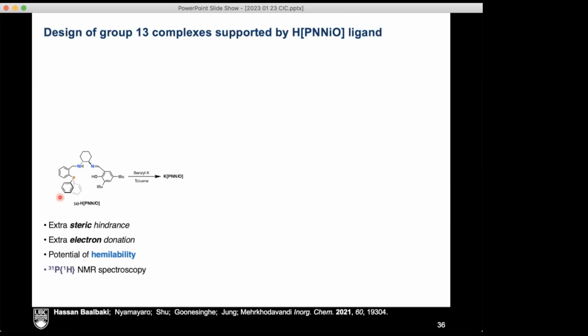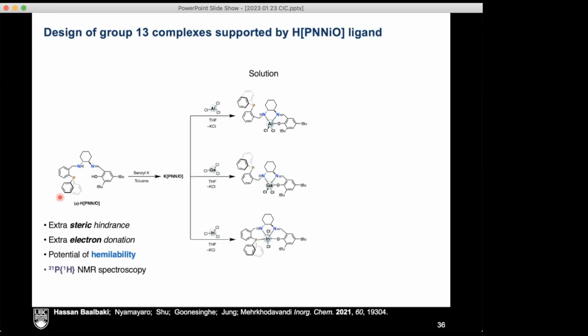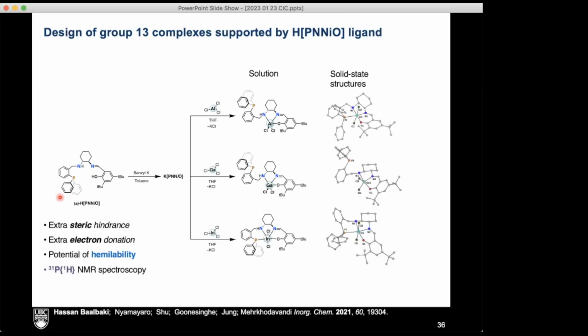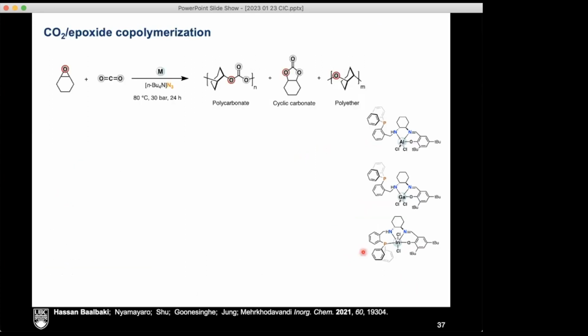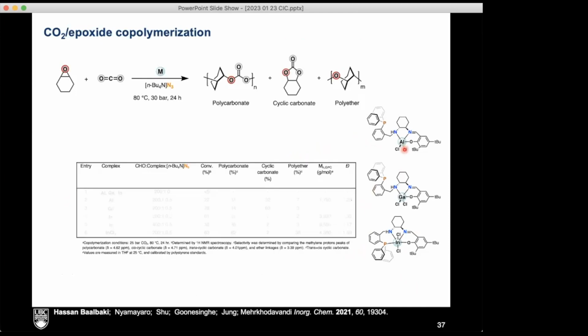And he rebelled and decided, okay, I'm not just going to work with indium, but I'm going to work with all of the group 13 to look at a comparison. Okay, fine. So he was able to isolate all of these compounds. And what he was able to show is, interestingly, that for the aluminum system in the solid state, the phosphorus coordinates, the gallium it doesn't, the indium it does. But when you're looking at in solution, it really is clear that aluminum and gallium, the phosphorus is not coordinated in solution, but in solution for indium, the phosphorus is coordinated. And that is really important in the catalytic discussion that I'm going to talk about.